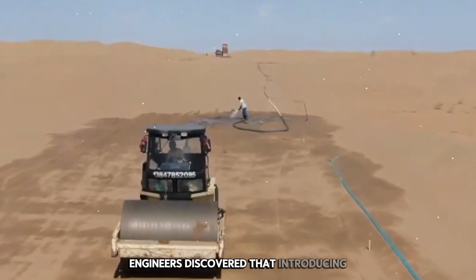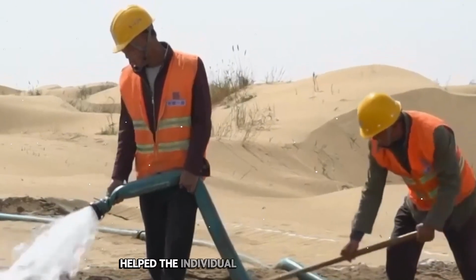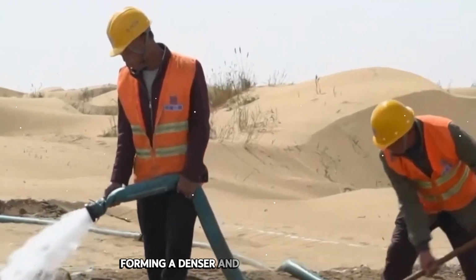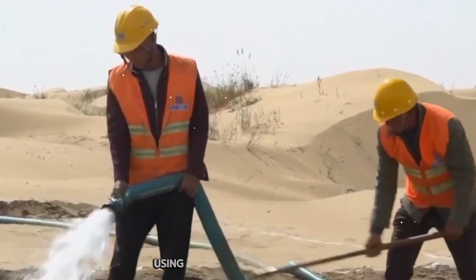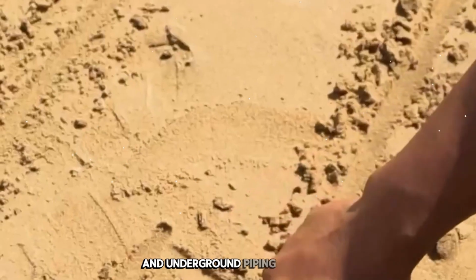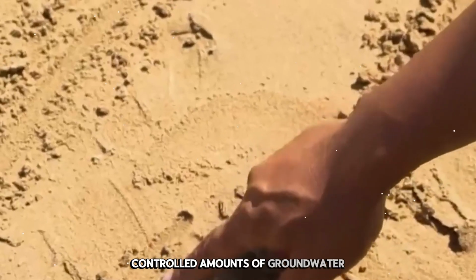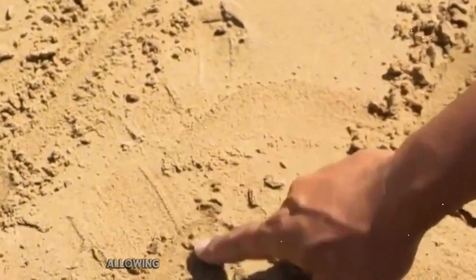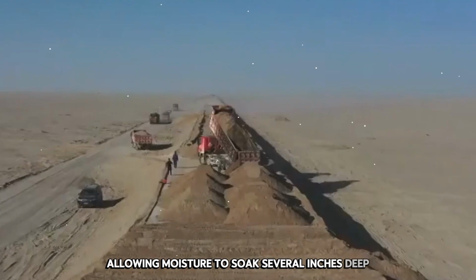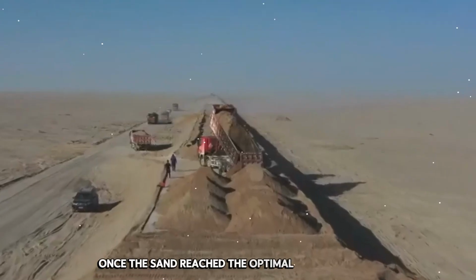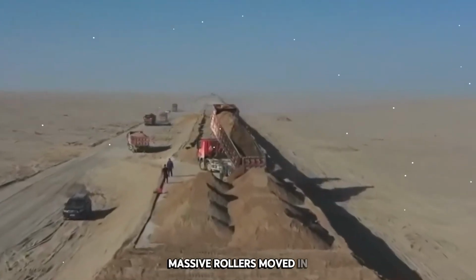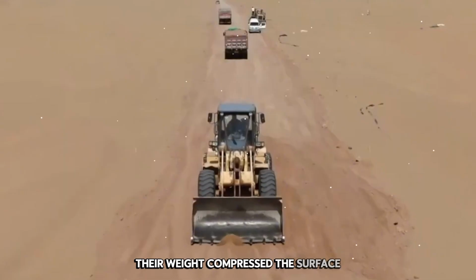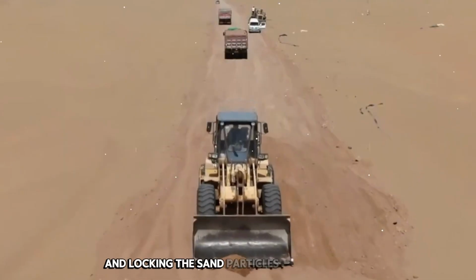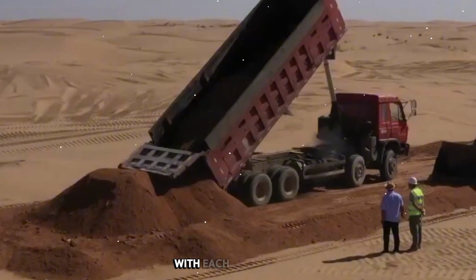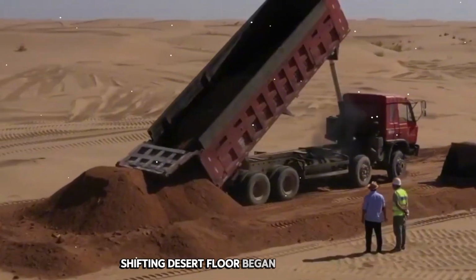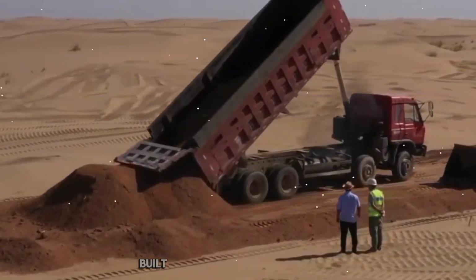Engineers discovered that introducing water into the loose surface helped the individual grains bind together, forming a denser and more cohesive layer. Using extended sprinkler arms and underground piping networks, controlled amounts of groundwater were evenly distributed across the site, allowing moisture to soak several inches deep. Once the sand reached the optimal moisture level, massive rollers moved in. Their weight compressed the surface, forcing out trapped air and locking the sand particles firmly together.